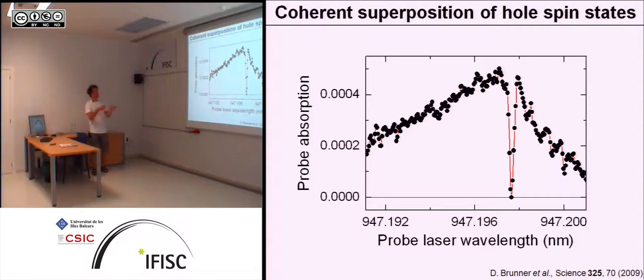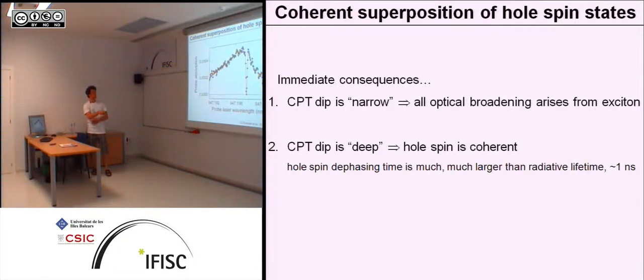So at least at these low coupling intensities of the lasers, that must mean that the hole spin is very coherent. The other thing is that the exciton line is very, very broad. I think we measured 8 microeV instead of 1, which would be the lifetime limit. So something is completely messing up the exciton. But in the end, this doesn't have any influence on the hole spin, because otherwise this line would be very, very broad. So these are the two messages.